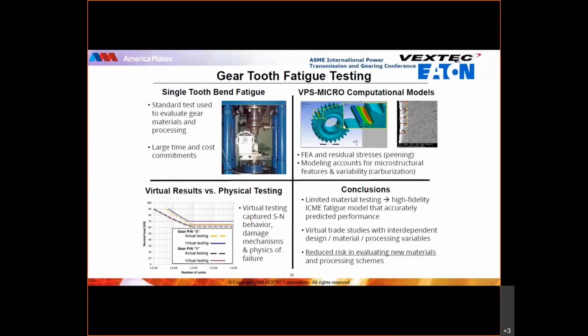And with Eaton Vehicle Group, we studied surface treatment effects on fatigue. Now, this wasn't specifically additive, but it does show a good example of how surface condition of the same alloy can have an impact on fatigue performance. So the Eaton Vehicle Group built gears for single tooth bend fatigue, but surface treated them differently. And we were able to characterize and model those. And if those can be characterized sufficiently, the software can model the impacts that those differences in surface treatment have